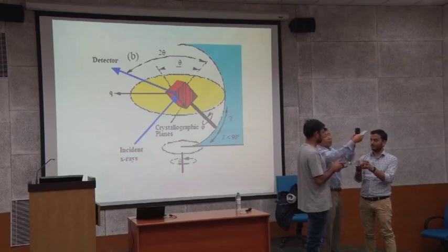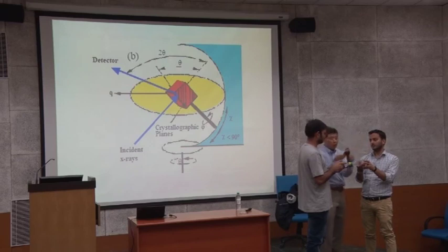So you have to access initially this plane, and move the chi angle to access. How much? This much angle. But if I want to access this plane, I want to change a little bit. If I want to access this one, I have to change a lot. You see that? The chi. So basically with your chi, you find the peak which is non-existing here, the off-axis peak.